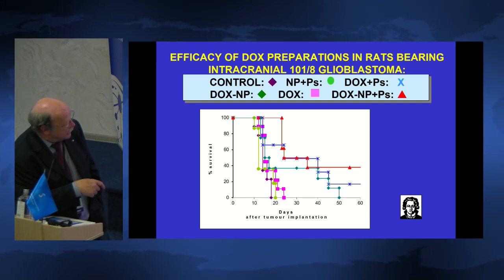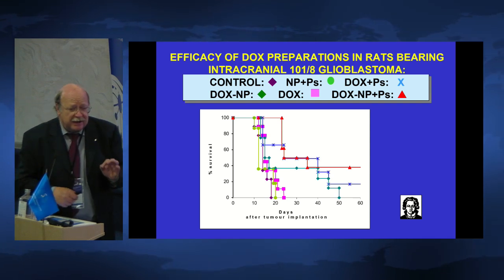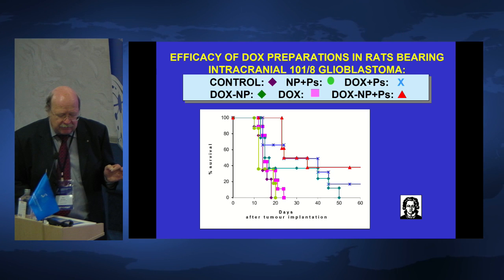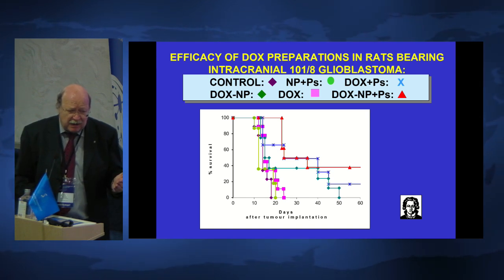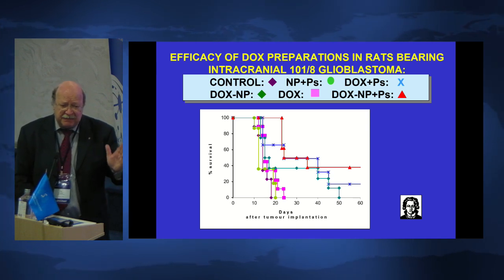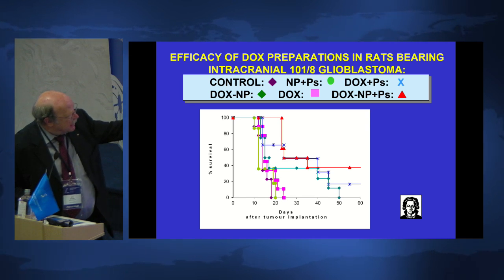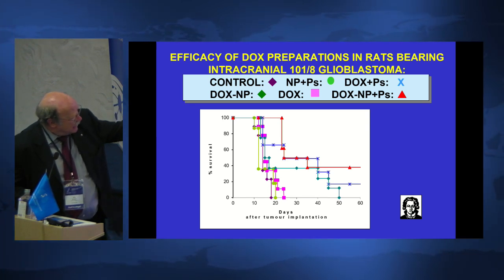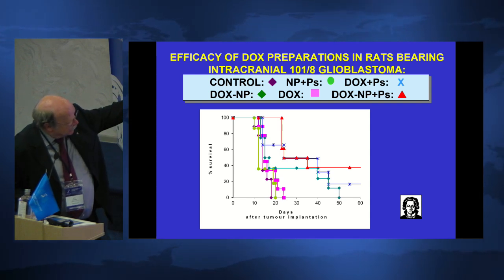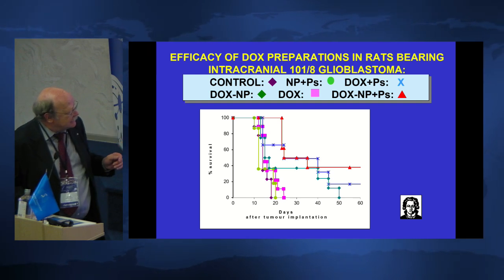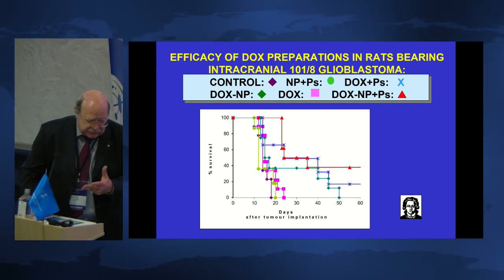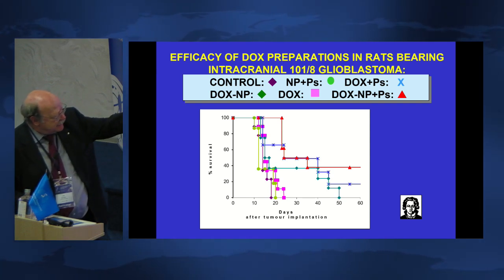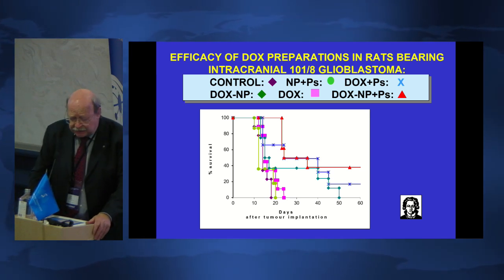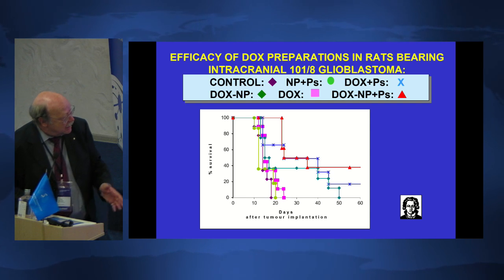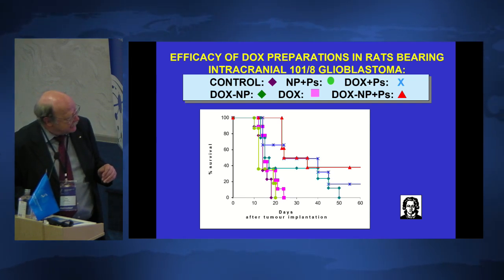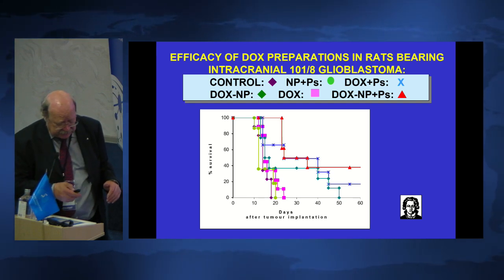And you can see on the left side, you can see the controls. The beauty of this glioblastoma, it's a rat glioblastoma. It is 100% transplantable, and the animals reproducibly die between day 12 and day 20. And that is the black-brown line on the right side. And then a number of controls we had here. And again, the particles with doxorubicin bound to the nanoparticles, overcoated with tween 80. You see the red line. This experiment continued to 60 days. And no animal died anymore. We repeated this experiment a couple of times.